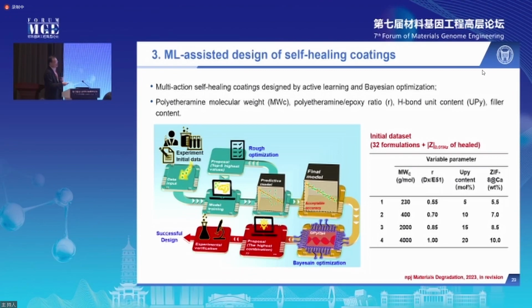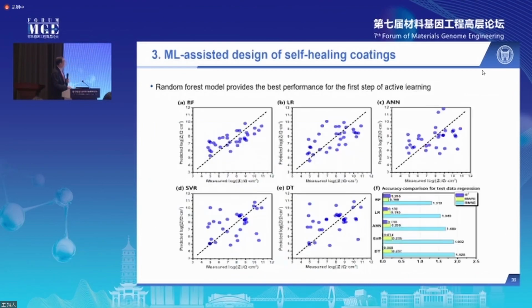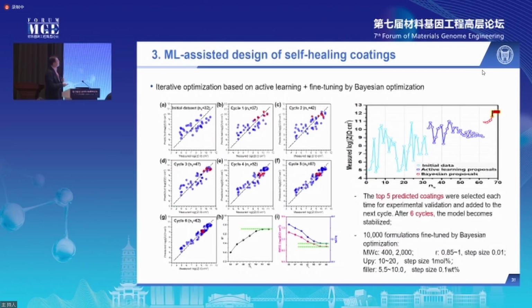So for each of the 4 parameters, we set 4 different levels. So 4 to the power of 4 gives us about 256 possible combinations. Initially we prepared 32 formulations and used them as input, and the corrosion resistance of the repaired coating as the output, and trained a model using several algorithms. We found that random forest performed the best for this type of small data set. And then we used this model to predict the rest of the 224 formulations and selected the top